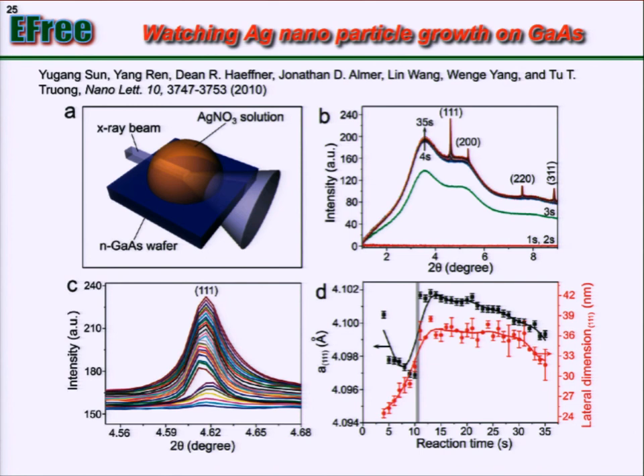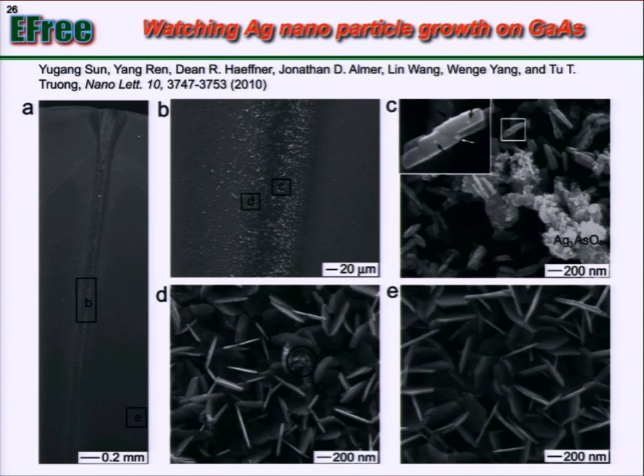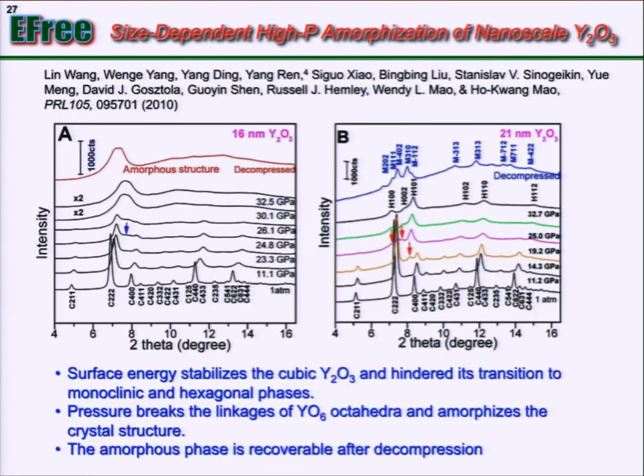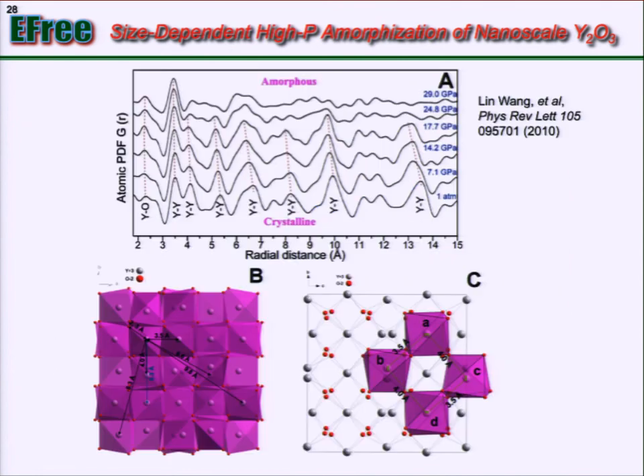Okay, let me move faster on some other subjects. Also at the synchrotron, we developed a nano beam technique to analyze the growth of silver nanoparticles on the gallium arsenide substrate. This again is something used broadly for energy application, and with the synchrotron nano beam, you can start to see all the detailed features of this. And there are more nano studies.